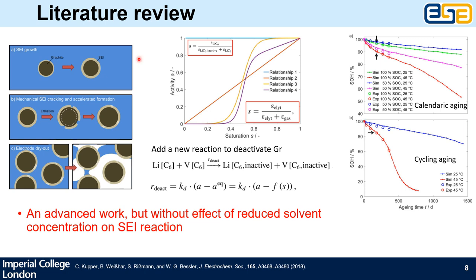In the third work, two parameters are proposed: the activity, which is the ratio between the active graphite and total graphite, and the saturation, which is the ratio between the electrolyte volume and the summation of electrolyte and gas volume. They assume different relationships between these two parameters, and with relations three or four they can fit the experimental data on the right-hand side well. However, they also ignore the concentration change of solvent. More importantly, they haven't discussed the effects of extra electrolyte outside the electrode but inside the cell package.